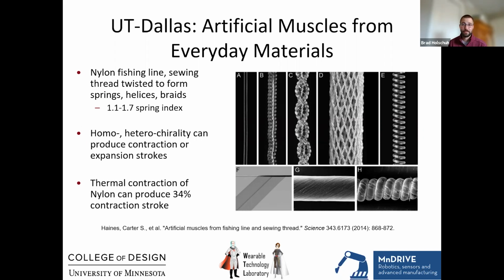So there's a really awesome paper from 2014, and there have been some follow-on papers since then, looking at, you can see the name of the paper, published in Science, Artificial Muscles from Fishing Line and Sewing Thread. So when you're talking about wanting to converge on a future where we can create textile-based robotic systems that mimic clothing, the closer that even the fibers themselves can get to natural fibers, or even the types of synthetic fibers that you find in your clothing, the better. You know, nickel titanium is great for what it does, but nobody currently buys clothing made out of nickel titanium. So if we can replicate what I just showed you using nylon, that's an even better future, because that's even closer to the dream of having clothing-based structures that have robotic properties.